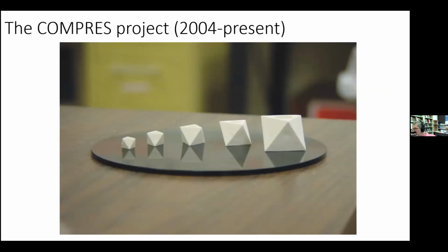So I'm going to just show a couple of slides about the COMPRES project, and then I'll talk about force. The COMPRES project is a project all the way back to 2004, where we did community development of multi-anvil assemblies, and we've had 5 different sizes of octahedra, which is how we basically make different pressures and different volumes. The largest is the 25 millimeter edge octahedron, and we use it with 15 millimeter cubes. Then we have this 18, and then 14, which is a 14.8, and then 10, 10.5. The two numbers refer to the octahedron edge length and the carbide truncation edge length, and then the 8.3.